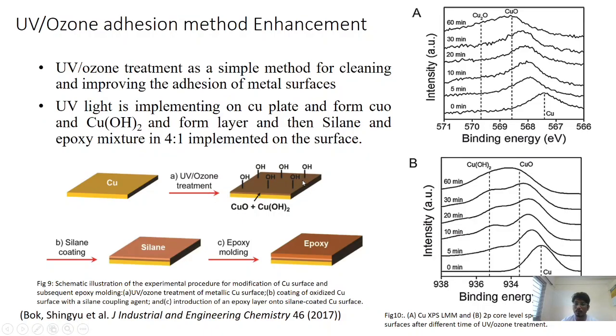So after the ultraviolet treatment of the copper substrate and formation of copper oxide and copper hydroxide, a silane coupling agent, which is an adhesion promoter, was applied to the ultraviolet or ozone treated copper, which ensures the uniform coating, as shown in the figure. Then epoxy is mixed with the hardener in the weight ratio 4:1, and this mixture was applied to the silane coated copper substrate and then cured using a hot press at 120 degrees Celsius and 7.5 megapascal for 30 minutes to form a solid epoxy layer, which is shown in the last figure of this procedure.